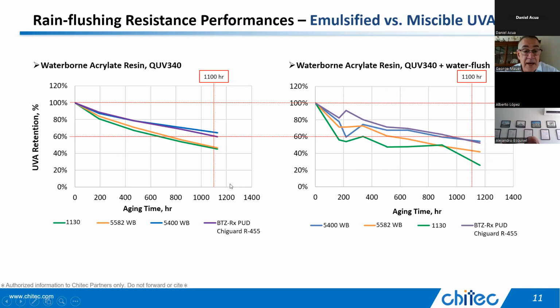So in this first test, we're going out about 1100 hours. And the one thing you can say is the 5400, which is the triazine, is definitely better. That does not migrate out at all. And this BTZRX is Chigard R455. BTZRX means a benzotriazole that's reactive, which was put into a polyurethane dispersion. And in those cases where there's very little migration, we see that the UVA retention is a fair amount better. But when you add the water rinse, which is what we see over on the right, you can see that the 1130 is starting to look quite a bit weaker.